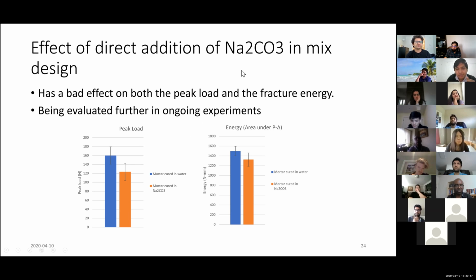So if sodium carbonate is added directly into the system during the mixing process, it starts reacting with alite and belite instead of going for calcium hydroxide. So it inhibits the natural hydration. That's why we observe a lesser peak load and lesser fracture energy. And this effect is still being evaluated in current experiments that I was doing, as to how much sodium carbonate is really bad for this.